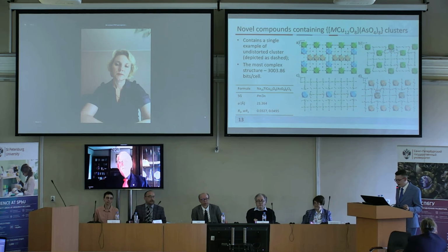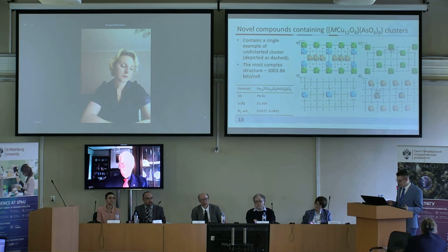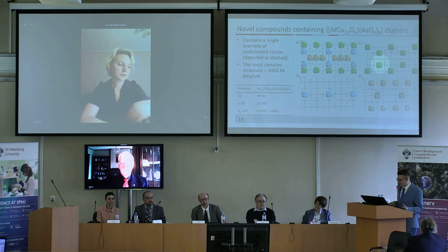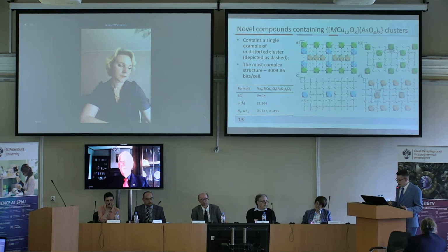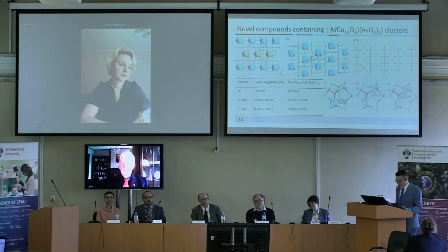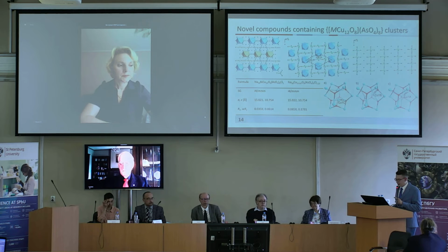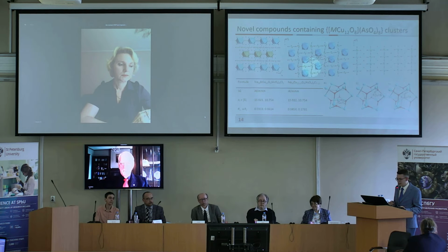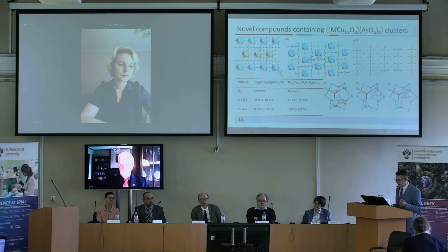So when fluorine is excluded, a new cubic phase crystallizes, which can be represented as layers inherent to the hexagonal packing. However, half the clusters are removed, and every other layer, every second layer, is rotated 90 degrees relative to the first. Between the two adjacent layers, there is an additional cluster. By reducing the oxidation degree to 3+, highly symmetric mineral analogs crystallize. The cluster packing is hexagonal, but the layers themselves are distorted, since there is a deviation of the angles between the cluster centers from 120 to 60 degrees.